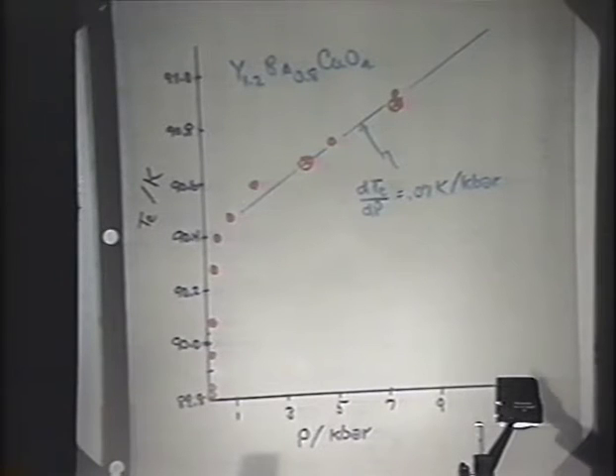And what we have is an enormous increase in T sub C, a rate of nearly 2 degrees per kilobar, which goes on for about half a kilobar. And then in our model, the kinks are straightened out, and the material becomes almost totally incompressible, and T sub C only changes less than 1/10 of a degree per kilobar.